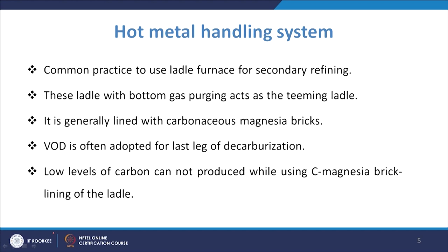Now, it is generally lined with carbonaceous magnesia bricks. So, that is the normal practice. Now, when we try to have even a smaller amount of carbon, for the decarburization, many a times we use the VOD process also. And while also using the magnesia brick lining of the ladle, then also we cannot ensure the low level of carbon that is what is found to be.